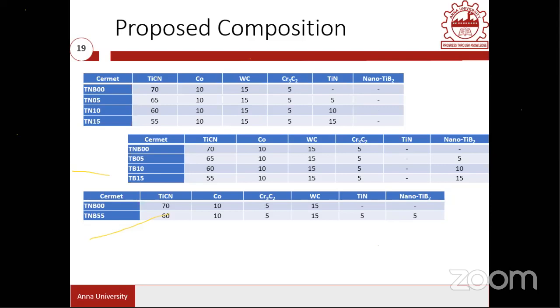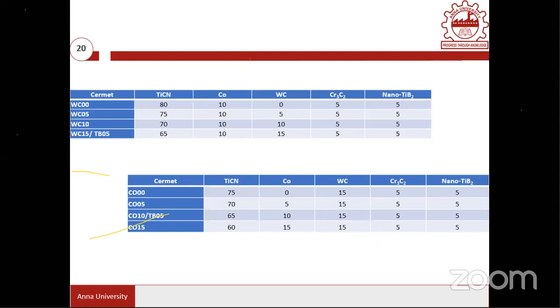Then for comparison, we have also made a composition which includes titanium nitride and nano titanium diboride, 5-5 composition. So that is taken. And TNB00 is represented as the material for our comparison, because no other addition is added here. So the TiCN, cobalt, Cr3C2 and WC are represented as a standard material, based on which we will compare other compositions in terms of hardness and toughness.